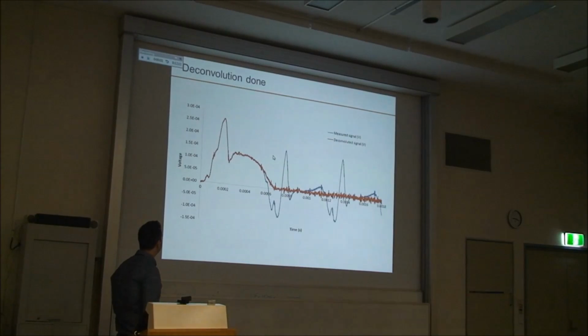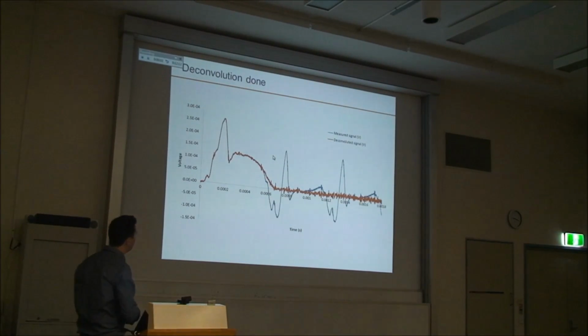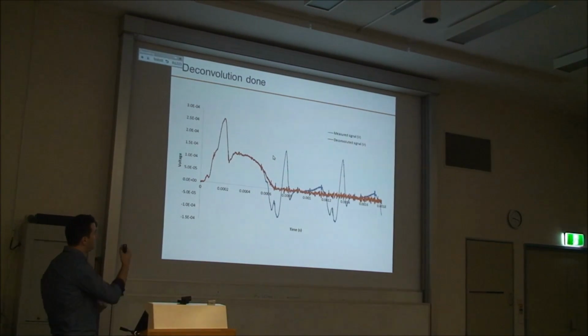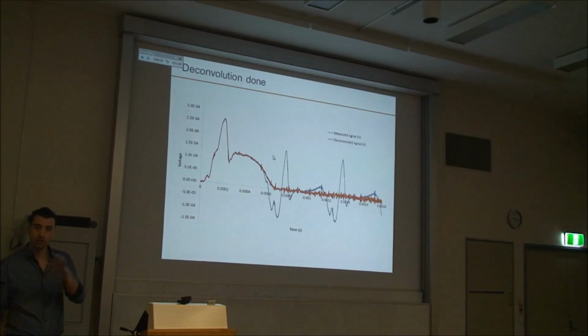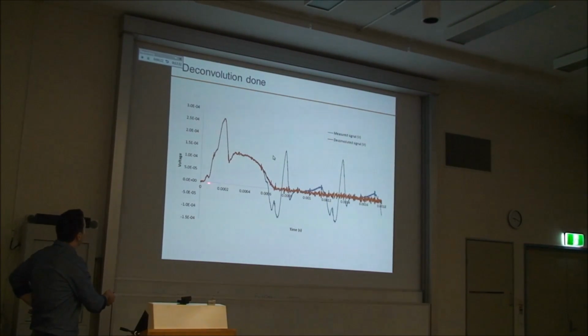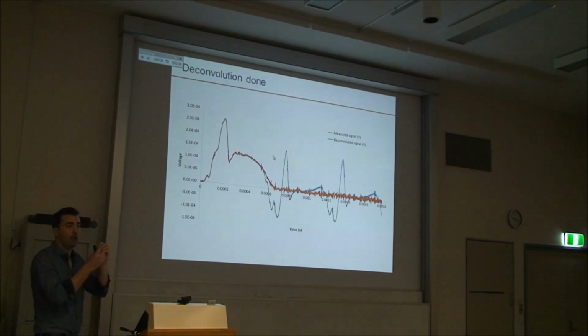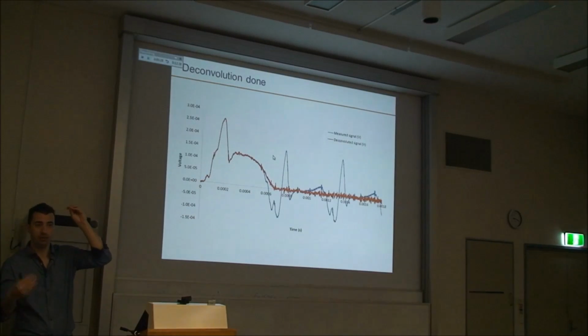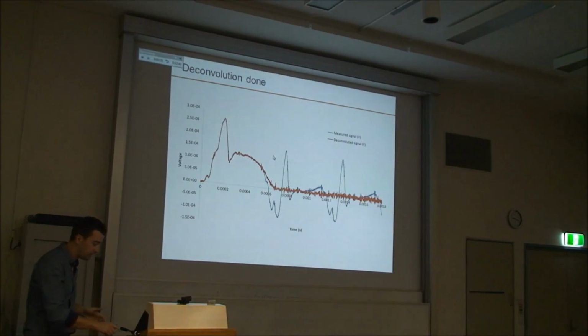The application is shown here. We've broken a particle. The blue signal is the signal sensed by the strain gauge. You can see that there is a fracture, and then the reflective signal comes back and travels in the rod up and down. The deconvoluted signal, after calculation of the prediction of when the wave is going to come back, is shown here in orange, and this comes back to 0, so it's like the rod would be infinite and we don't have the reflection coming back.